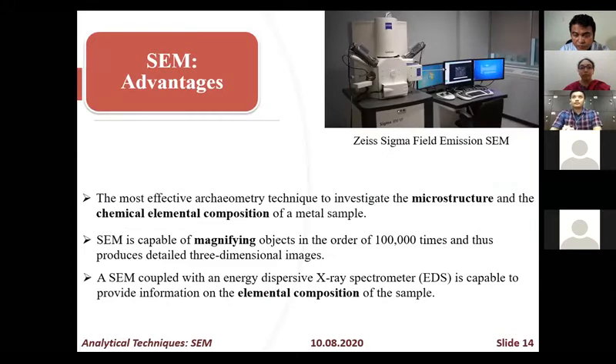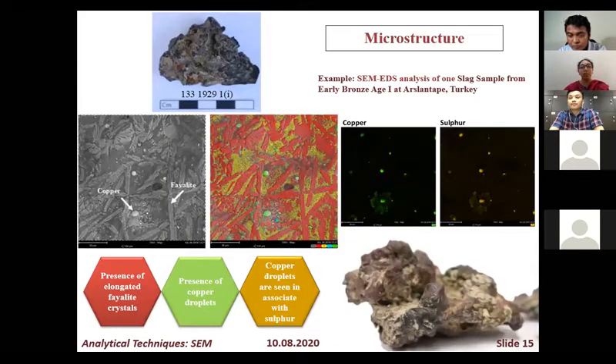SEM is very effective for chemical elemental composition and for the microstructure, and most importantly, SEM can magnify objects up to 1 lakh times. It can also give the elemental composition. For XRF, we know that in our sample we have iron, silicon, aluminum, copper, sulfur. SEM will show how they are distributed. For example, I can show the result for the same slag sample.